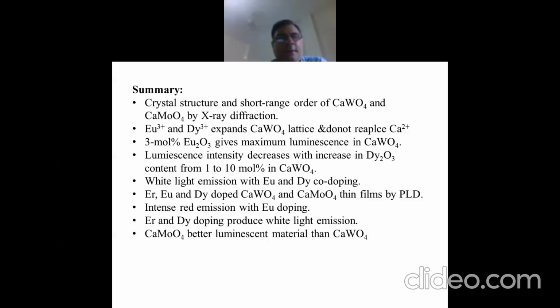Erbium, europium, and dysprosium co-doped calcium tungstate and calcium molybdate thin films can be prepared by pulsed laser deposition with very good stoichiometry. Intense red light emission on europium doping, and erbium and dysprosium produce white light emission, and calcium molybdate is a better luminescent material than calcium tungstate.